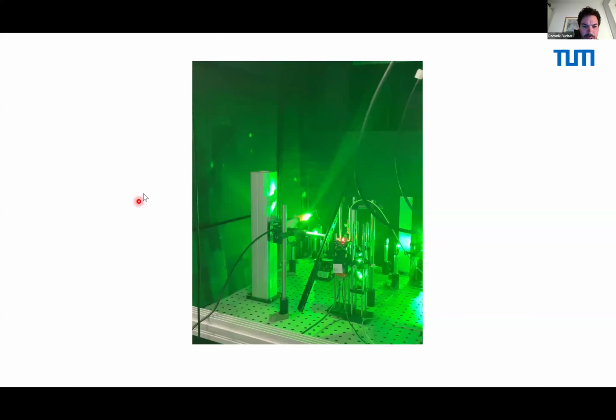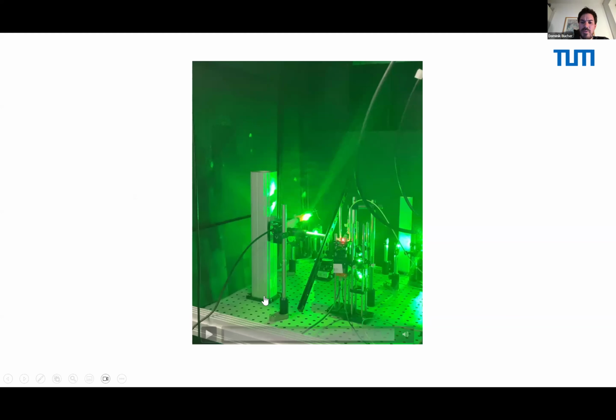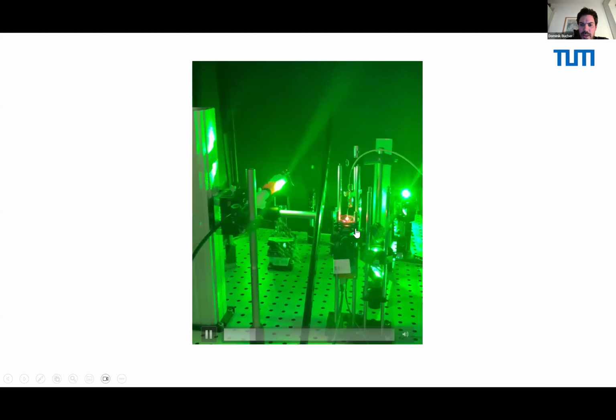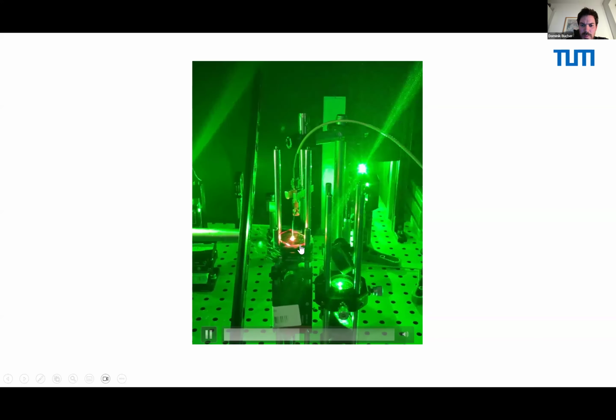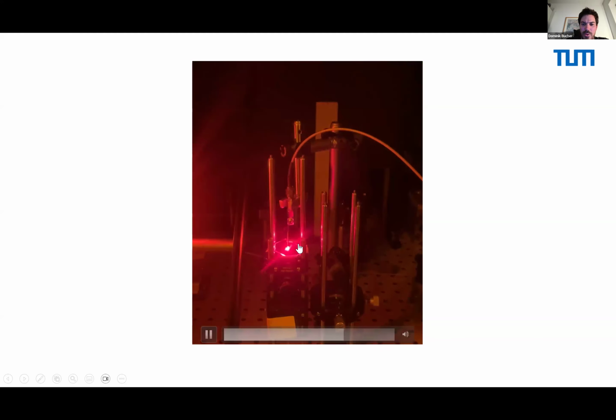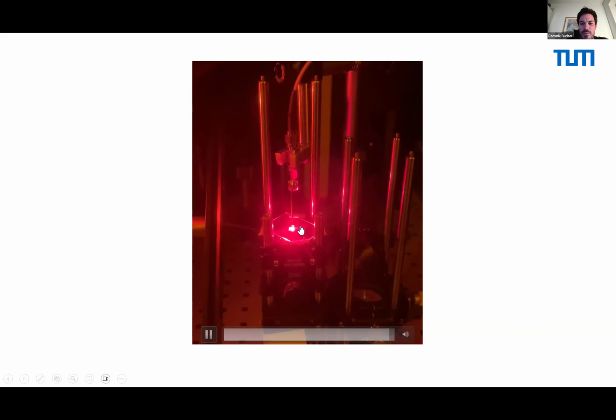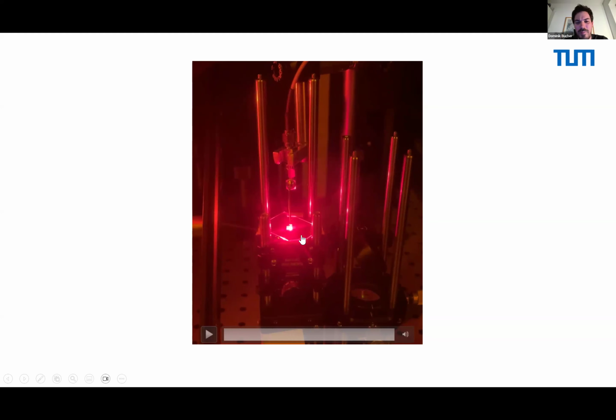So how does it look in our lab? So let's see if I can start this video. So that's a typical experiment setup we have in our lab. As you see here, you see a lot of green light. And I will just show you here the red fluorescence of our NV diamond chip. Let's see if this works. Doesn't work, huh? Now it works. So you see here basically this 2 by 2 millimeter diamond sitting, and you see the optics around. Now, if we use laser goggles, which block the green light, we see the very highly fluorescent NV diamond. Again, what we used here is a very highly doped diamond to visualize the effect much more. And what you see more here is the microwave transmittance going on the diamond, and on the bottom we have some optics to collect the fluorescence light.